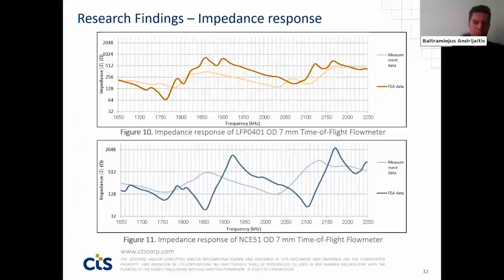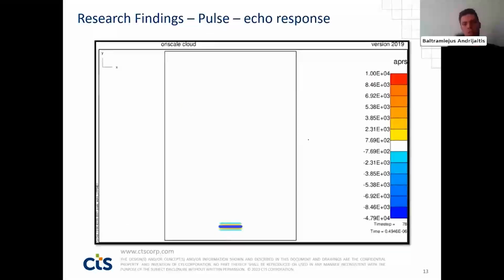So here, as well, we have a comparison of lead-free and lead-based transducers. Again, on the curves, we can see some differences. These differences could come from various sides: from material metrics inaccuracies, quality of assemblies, and differences in geometry of the ceramics, because in the real case, we use ceramics with wraparound, and in the model, we used the edge-to-edge electrode. However, again, differences are not significant. It's up to 5%. So the model was considered good to continue.